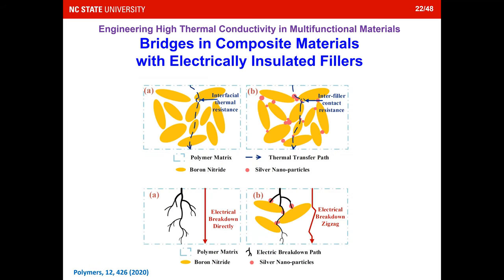So what's the reason we have those good combinations of properties? We think the reason is that they also form a network. If you just have the boron nitride two-dimensional sheets, it's very hard for them to get really contacted. There is a lot of interfacial thermal resistance between those sheets. Adding those nanoparticles in between actually helps to bridge those sheets and helps with the thermal transport. And also, because the bulk part of the boron nitride is not conductive, you don't have to worry about the electrical properties. But in terms of the breakdown voltage, this definitely helps a lot.